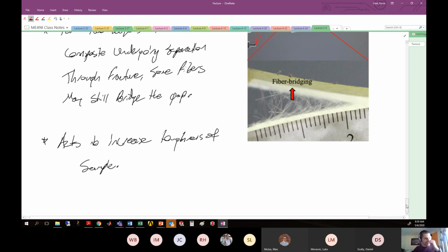Now, what's interesting is that if I'm doing a test, I need to create a sample. When I first create the sample, I do that by putting a piece of Teflon into my piece so that I have this starter crack that exists between two different layers. When I have that starter crack in there, there is no fiber bridging at that particular location. There are no fibers spanning that layer. I've made sure of it because I've included this Teflon piece. So when I first start the test, there is no fiber bridging. However, as I progress through the test, my fiber bridging is increasing and increasing because I am getting further and further away from that Teflon insert inside of the piece where the fibers originally were. So what this leads to is some interesting phenomena in the R curve for the sample.